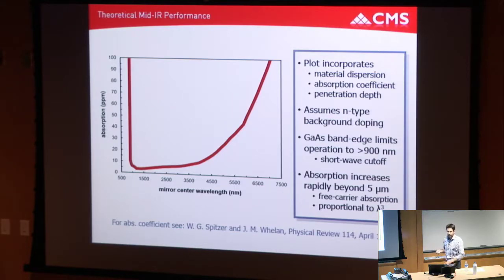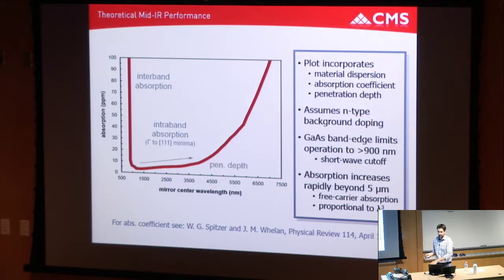So dispersion is taken into account here, the change in absorption coefficient as a function of wavelength, from these beautiful old papers, right? This 1959 paper that just studied the absorption coefficient in gallium arsenide as a function of doping and wavelength. We're looking at the change in penetration depth, and then we're assuming an N-type background, which we ideally want in our MBE-grown material. Obviously, the band edge cuts us off at 870, and then we have this plateau from these intraband processes from the global minima to these local 111 minima that give us finite absorption there. And then the penetration depth kicks up. So as the mirrors get thicker, the field penetration is a little deeper, so there's a slight tilt here. And then free carrier absorption is the killer as you go to longer wavelengths.